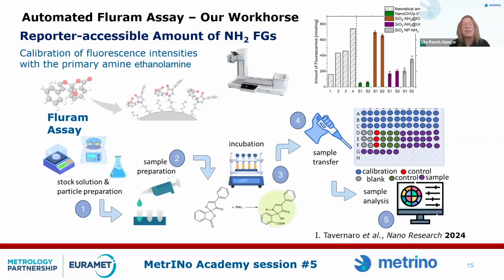So this is how we did this automation, very simple, with a pipetting robot and a microtiter plate. Thereby we developed a protocol. We eventually published this, and we use a primary amine, ethanolamine, for calibration, because when you do an optical assay, you need to calibrate the fluorescence intensity measurements.